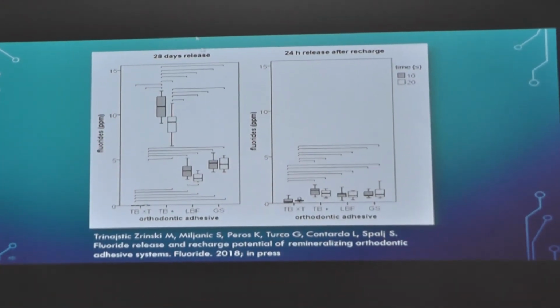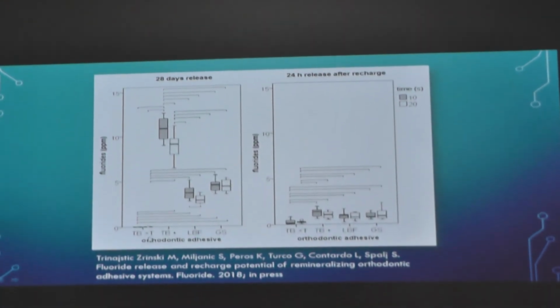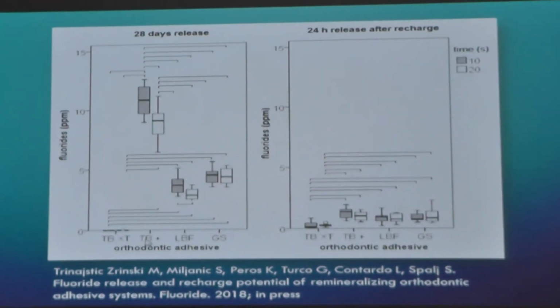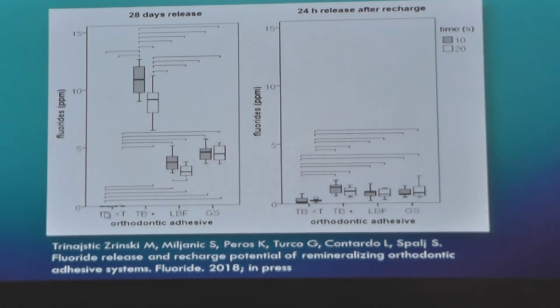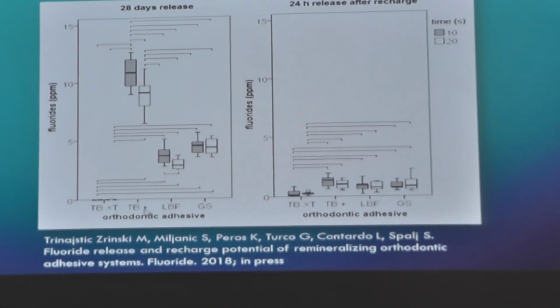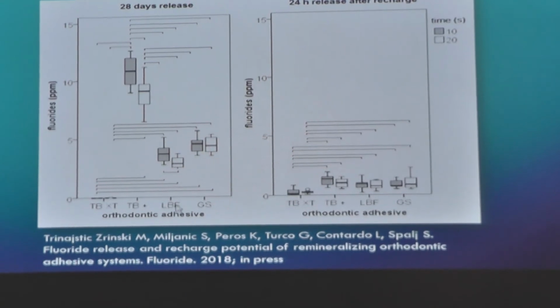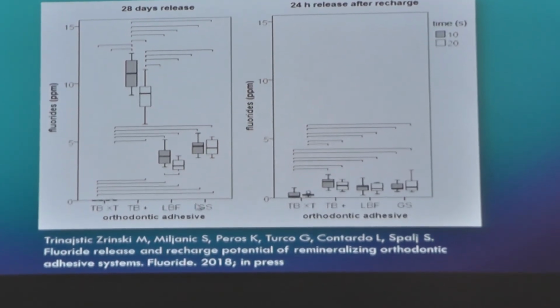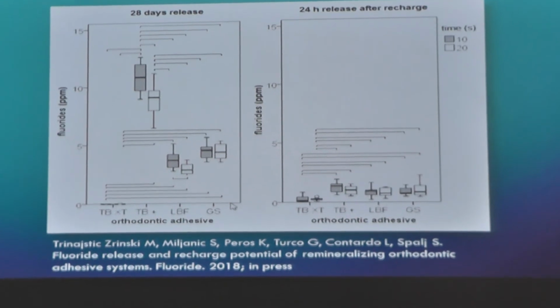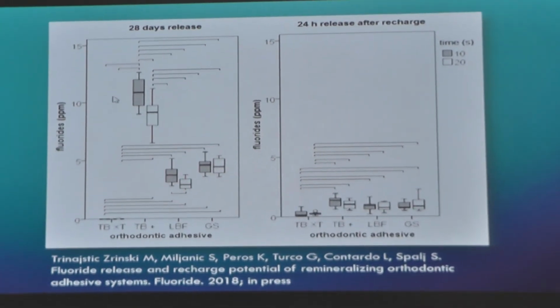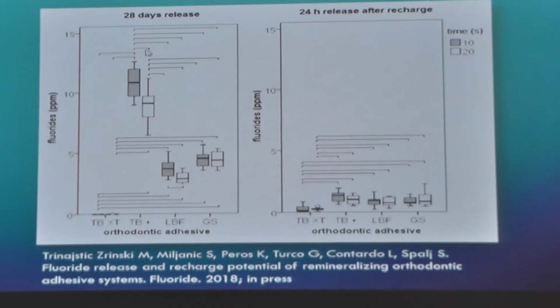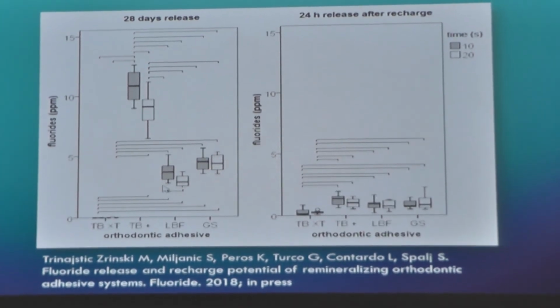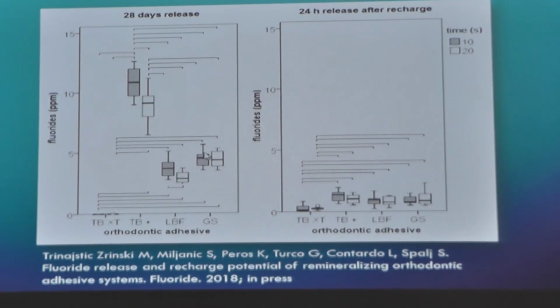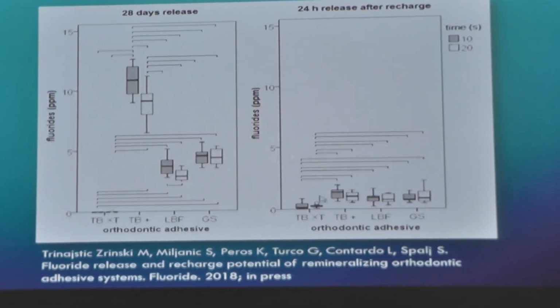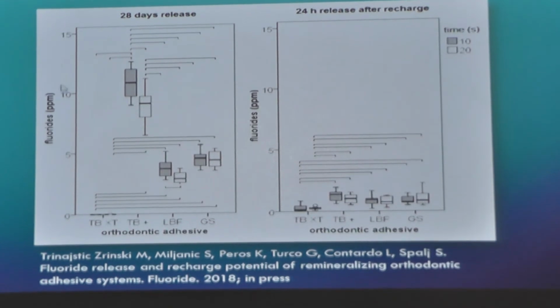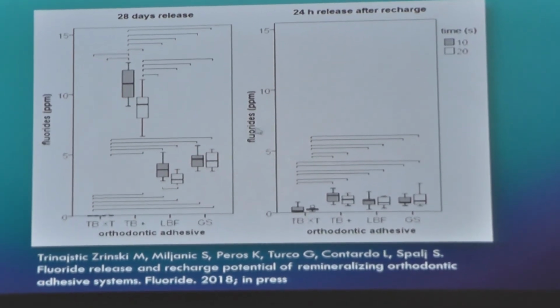So what we found is that these adhesives containing fluoride, so this is the control Transbond XT, this is Transbond Plus, which is the equivalent of Transbond XT with the fluoride, and this is Light Bond with fluoride, and this last one is a resin glass ionomer combination. They showed, so Transbond Plus showed superior ion activity than the other two fluoride containing adhesives. However, this is not a high release altogether.